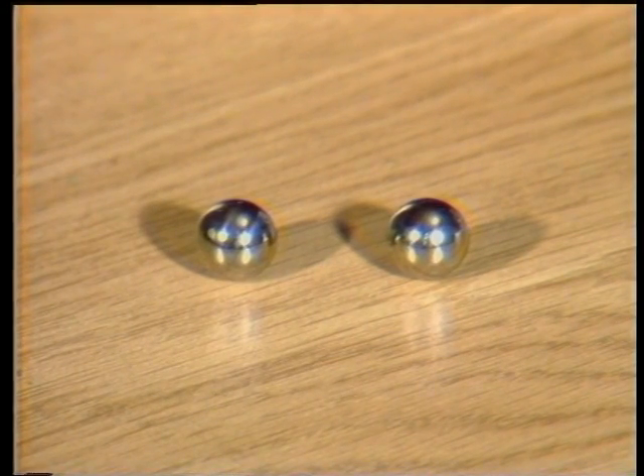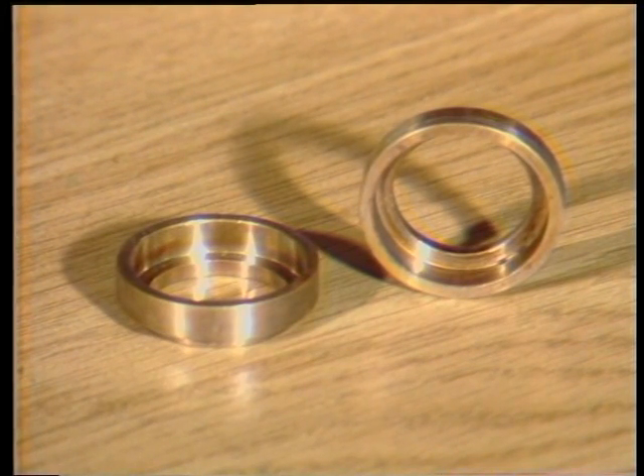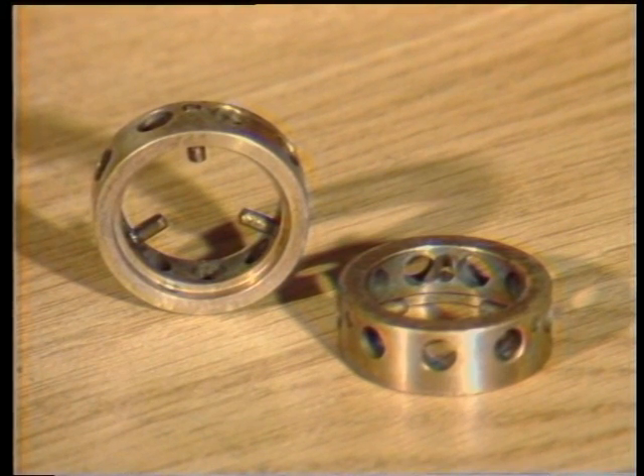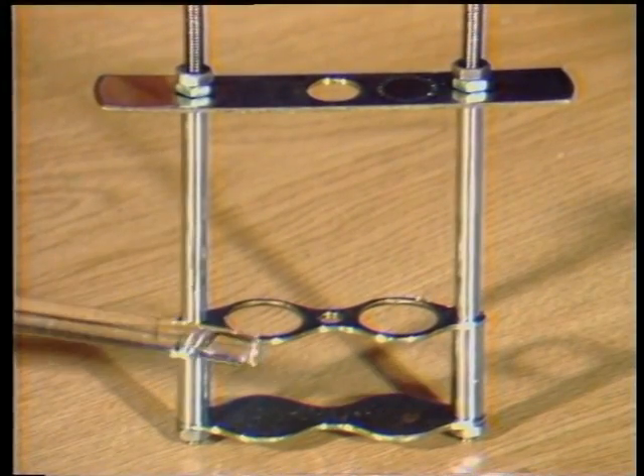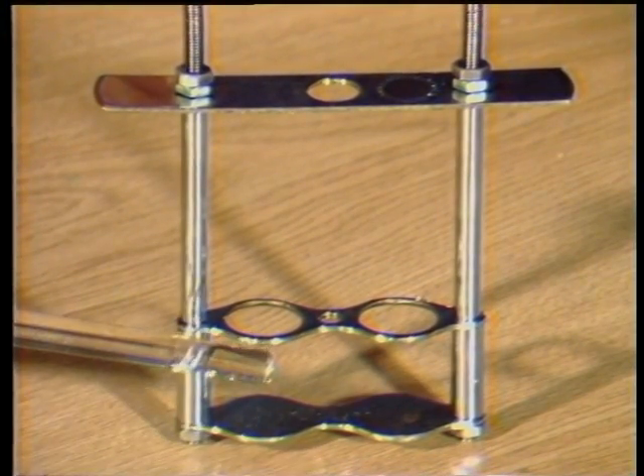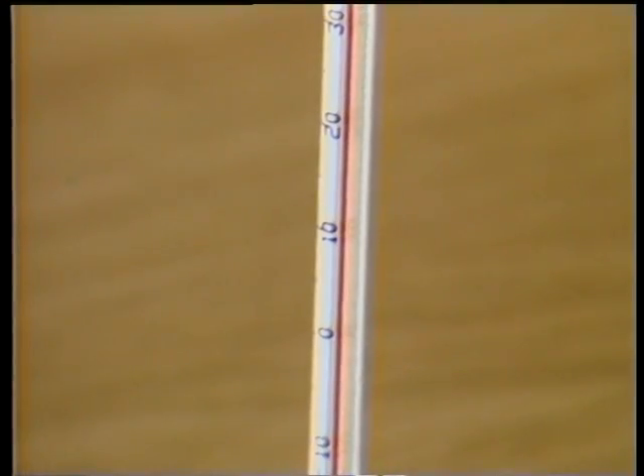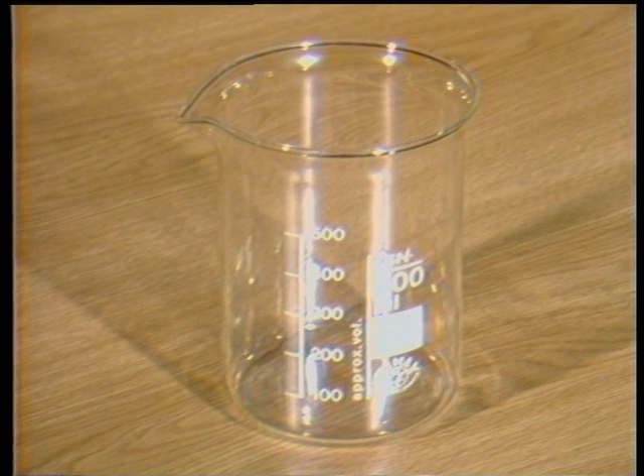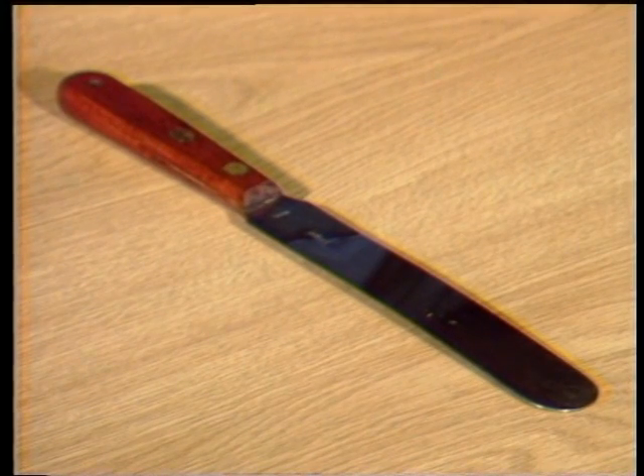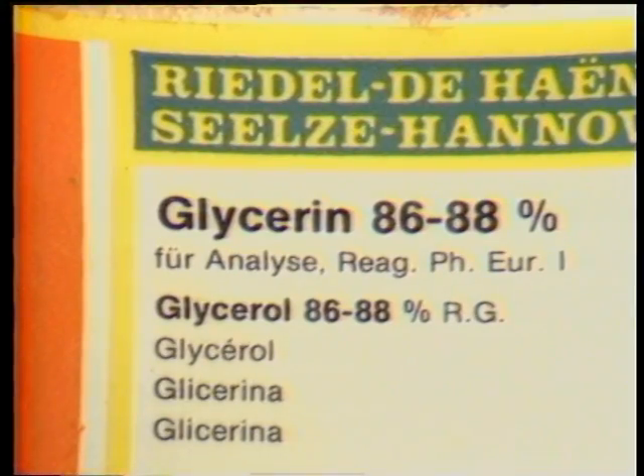2 steel balls, each having a diameter of 9.5 millimeters and weighing 3.5 grams. 2 shouldered rings, each having a diameter of 23 millimeters and a height of 6.3 millimeters. 2 ball guides made of brass. A ring holder and bottom plate 25 millimeters apart. A thermometer. A heat-resistant glass beaker. A spatula. A small metal plate. Glycerine and talcum powder mixture. A heating unit.